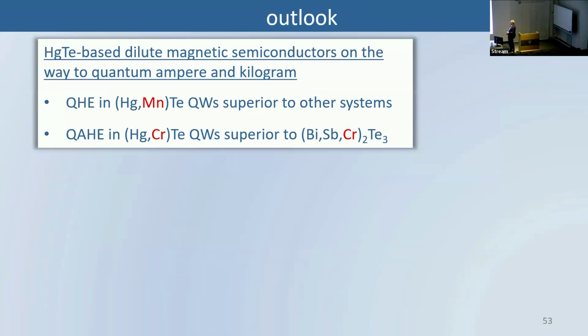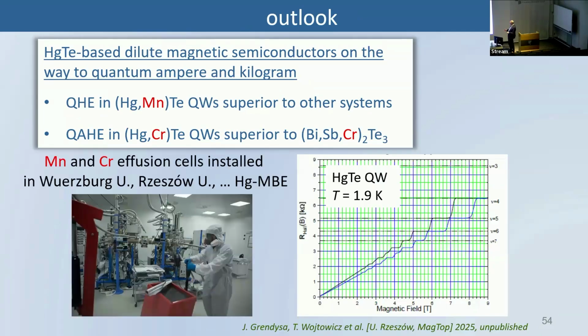Another outlook: mercury telluride is a good material. Particularly, the quantum Hall effect should be expected in very weak magnetic field in mercury manganese telluride. And in chromium samples, we expect the quantum anomalous Hall effect. Such material can be produced by MBE; it's available in Wuerzburg, it's available in Rzeszów. And the very results from Rzeszów for the quantum Hall effect in quantum wells of mercury telluride were obtained just two weeks ago or something like that. So these are very recent results. Thank you very much for your attention.